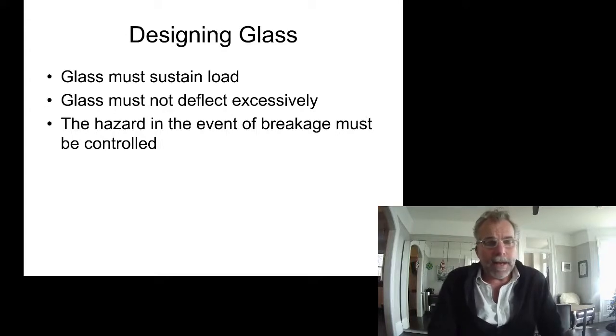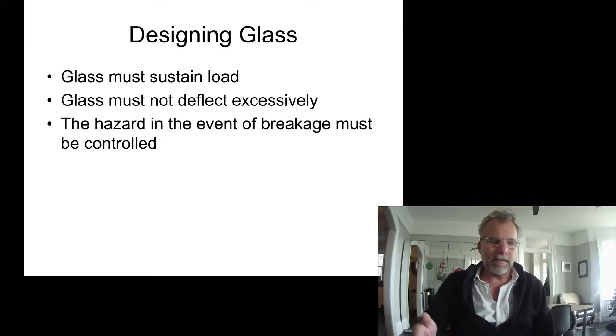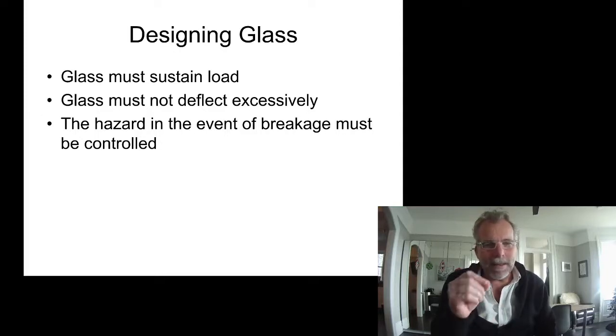There wasn't anything wrong with the glass. The glass is fine. Just the natural rate of background breakage is something like 1 piece in 1,000. But when you're building 10,000 units a year of condos and they all have glass guards, then it's an epidemic of failing guards, just with the normal statistical background breakage rate. The failure is not due to any actual damage. The failure was little bits of nickel sulfide and chemical imperfections within the glass. So very little tiny things, but they would start to propagate and crack.